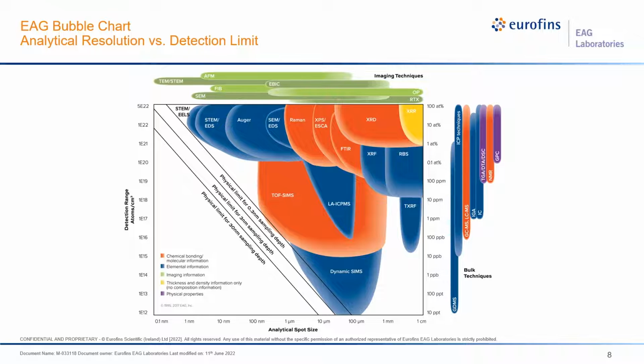1% and 0.1% atomic. Only dynamic SIMS, shown in the blue bubble, reaches all the way to the bottom of the graph. Only dynamic SIMS has detection limits below 10 parts per billion with analysis areas of less than 10 micrometers. And these detection limits can be obtained with high depth resolution.